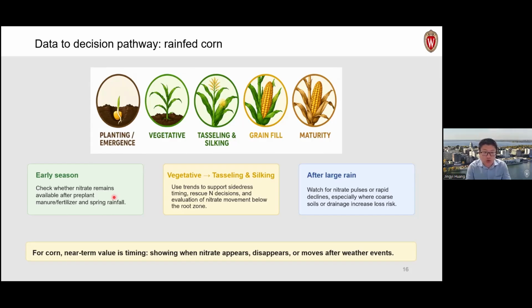So we can figure out the dynamics of the nitrogen during the early season of crop establishment, especially with changes in early season temperature compared to historical years. During the growing season, we can also use it to find the critical timing where we should keep a better eye on the nitrogen status, making sure we are not under, but also not over applying nitrogen fertilizer. What can be even more informative is that, as you see over recent years, there are heavy thunderstorms, and those could affect the availability of nitrate in the soil. So instead of just guessing the available nitrogen status, we can use this data to get real-time insights about the remaining nitrate value.